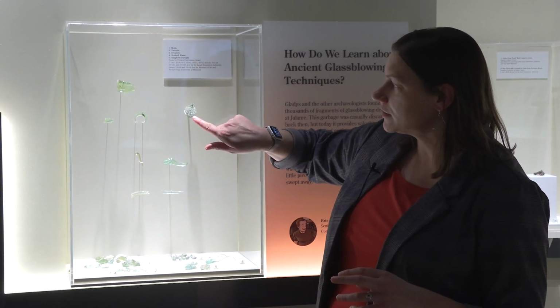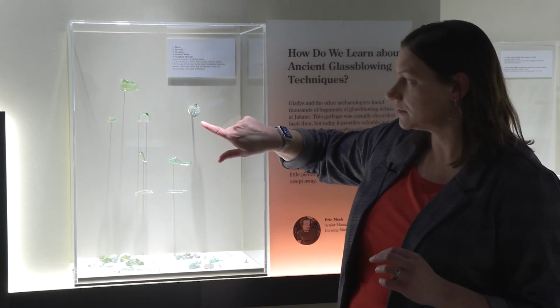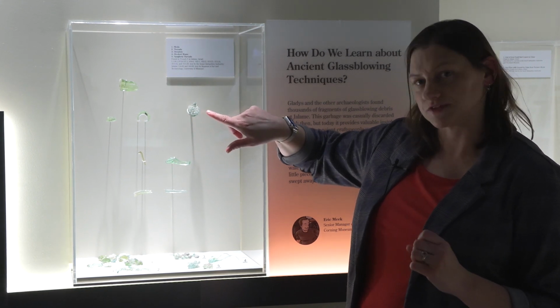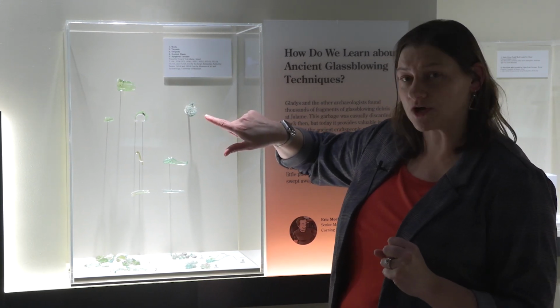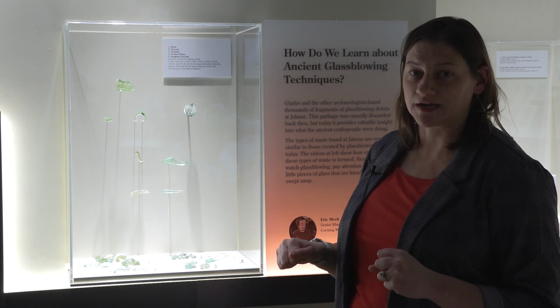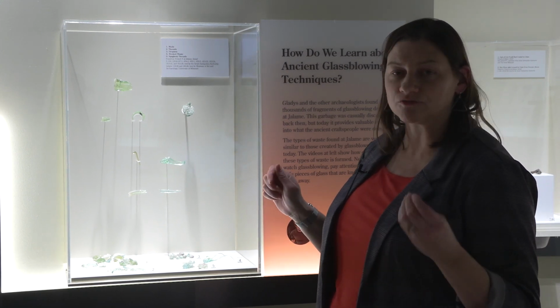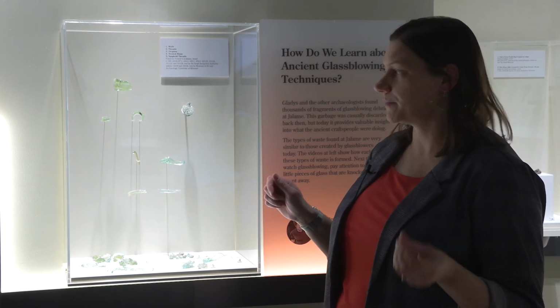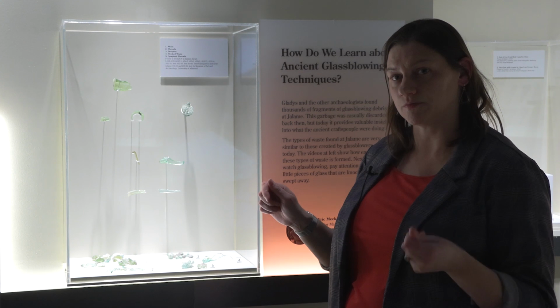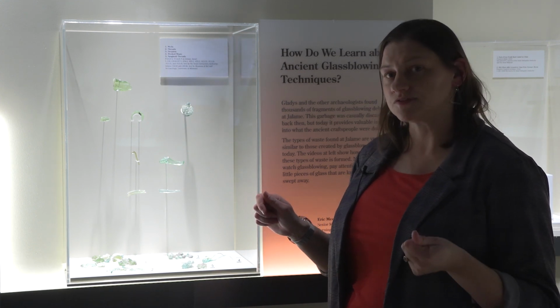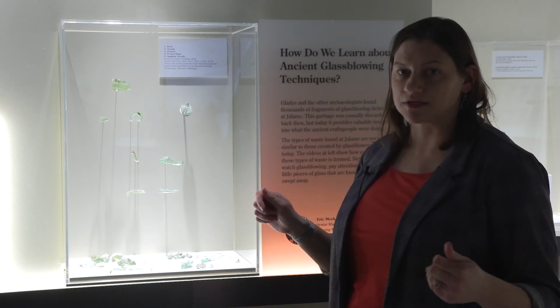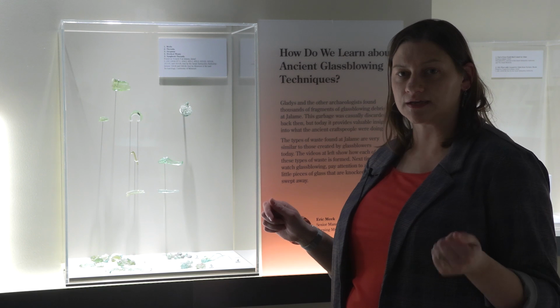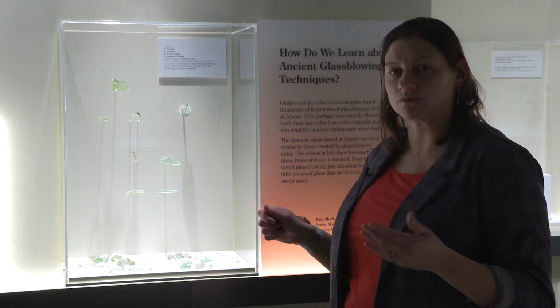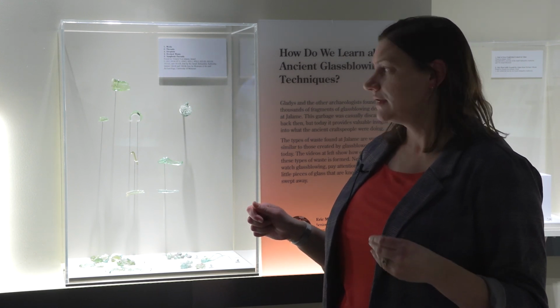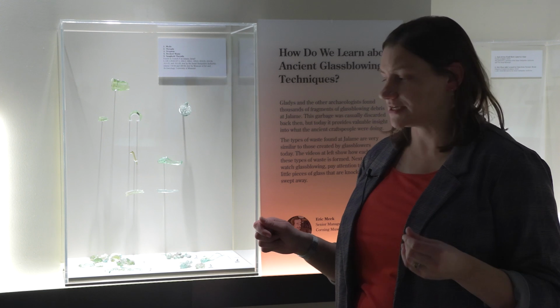So this little dark fleck in this particular moil is a piece of iron scale. And that's how we know that the glassblowers were using iron blowpipes, because that iron flaked off into the glass. This was the part of the glass that was in contact with the blowpipe. And that might have been one of the reasons why these weren't recycled or remelted, is because the glass workers recognized that higher levels of iron would further contaminate their glass, and they tried to keep it pretty pristine.